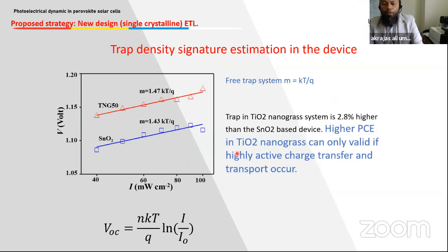Actually, as I mentioned earlier, TiO2 intrinsically contains a large density of defects, larger than SnO2. It is true that in our device, using the relation between the VOC of the device and the carrier density during the photovoltaic process, we can estimate the trap density signature. We get this trap density signature in the device using nanograss is much higher compared to SnO2, around 2.8% higher than the SnO2-based device.